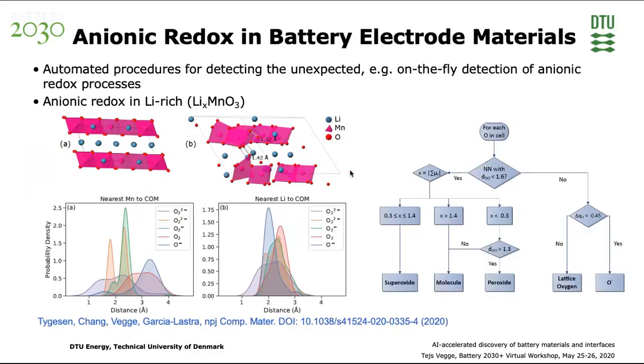Another thing which the BigMap procedure is really supposed to do is also to automate procedures for detecting the unexpected. In this case, it's work by Alexander Tygesen on the fly analysis and detection of anionic redox processes. So what Alexander did here was to set up an automated framework for analyzing when you have anionic redox processes occurring, the lithium-rich lithium manganese oxide here, by using the oxygen-oxygen distances as well as the local magnetic moments to identify which of the anionic species are active in the anionic redox processes, analyzing also how close they are to the manganese, how close they are to lithium.